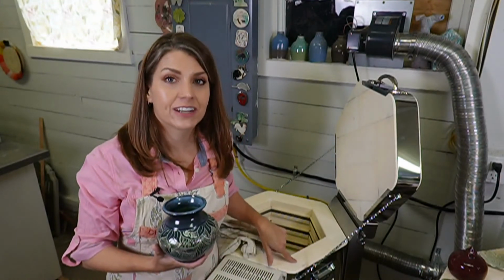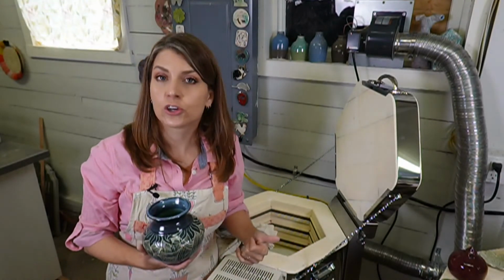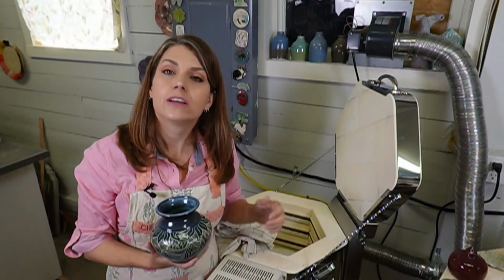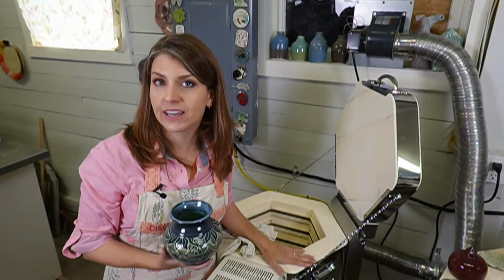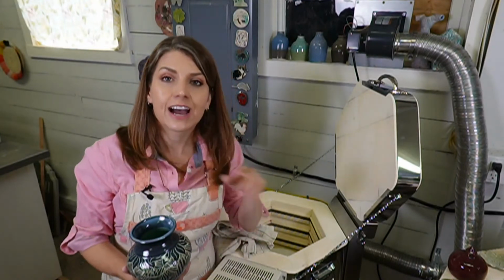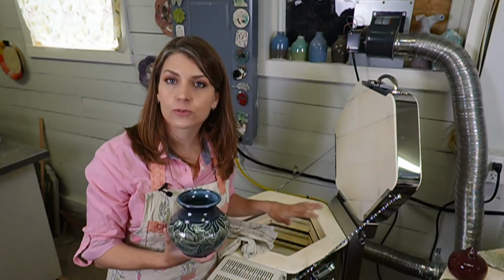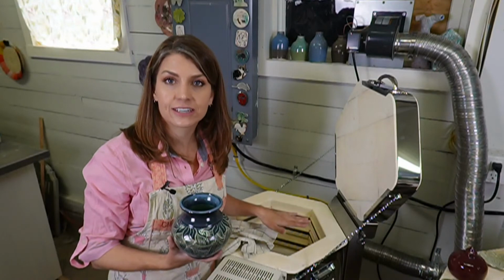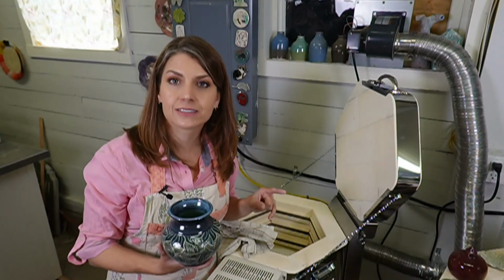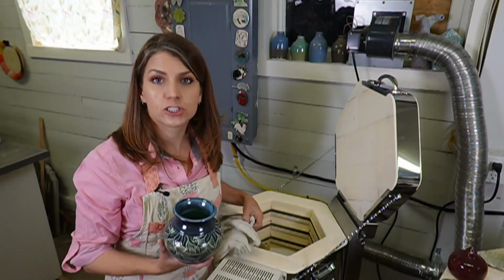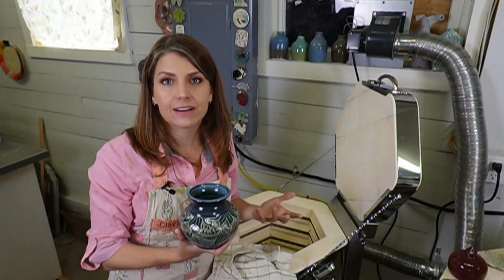Now, cone 5, but if you go to 7, and if I ever wanted to go to 10, I couldn't go to 10 with a 120 current. So this would allow me to go to cone 9 if I needed to do a test of a glaze for my gas kiln. I wouldn't get the same result as a reduction firing in my little electric kiln, but I would see if the glaze melted. So I at least could test for that. So for me, this was the smartest thing to do. But over time, your kiln works harder when it's not to 240.